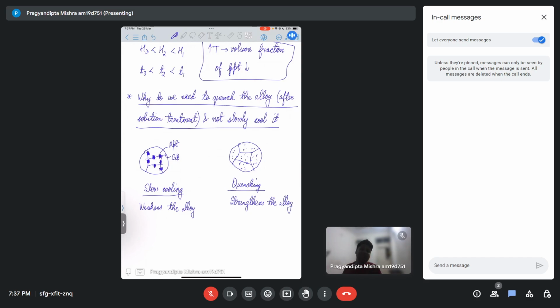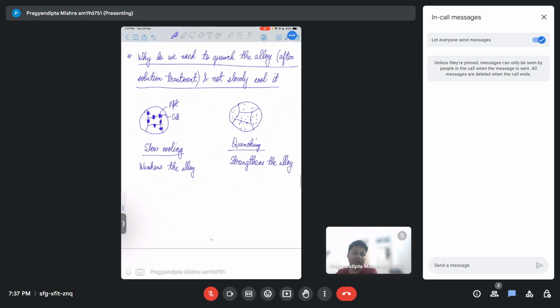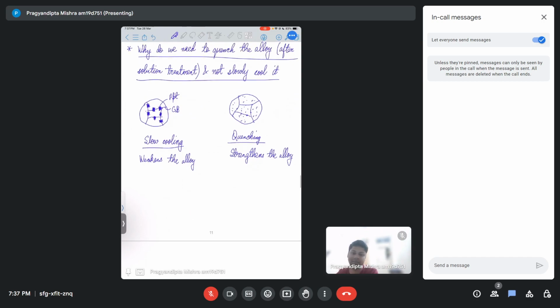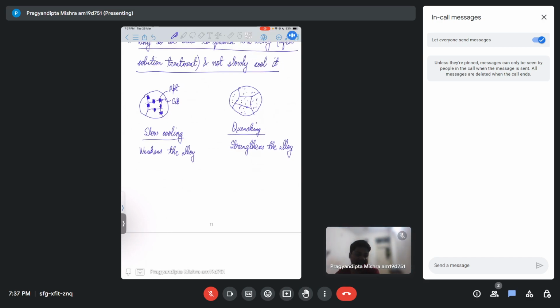So you can think of it like if the precipitate is getting formed at the grain boundary, what is happening is now dislocations which were interacting with grain boundary and were interacting with precipitate, both are now directly interacting together. So instead of strengthening, it is now weakening the whole thing. But now if precipitate and grain boundary are separate, they can interact freely, and then you will see a more strengthening atmosphere within the whole alloy system. Okay. So this is about precipitate strengthening.